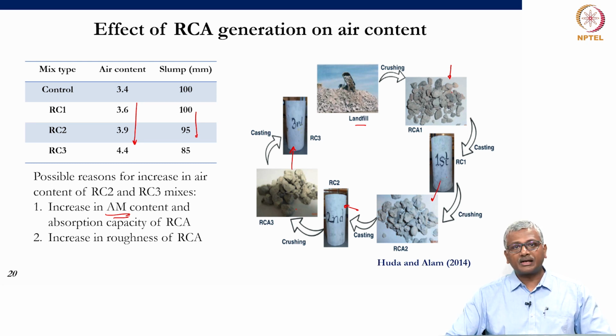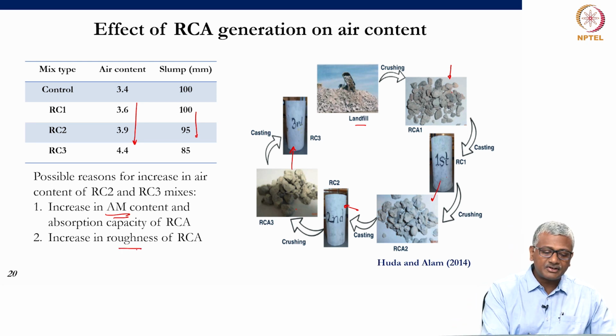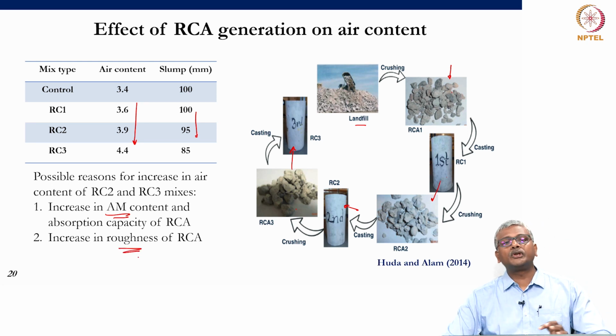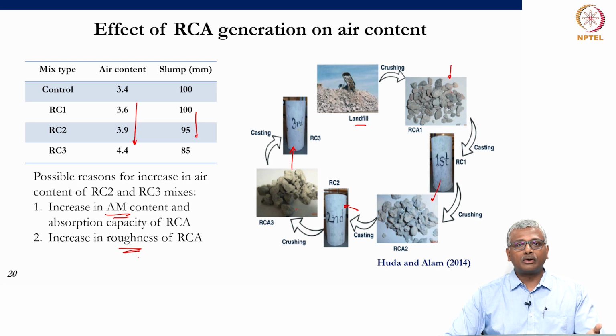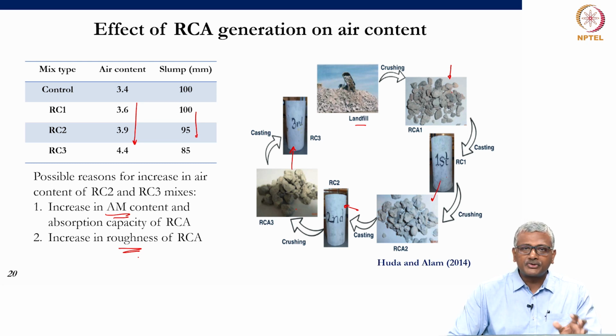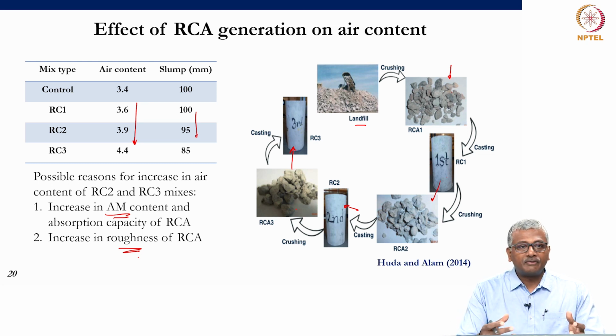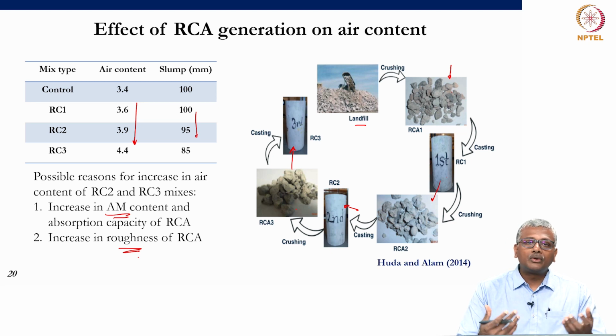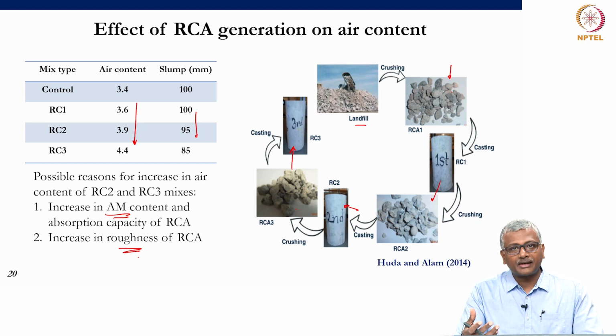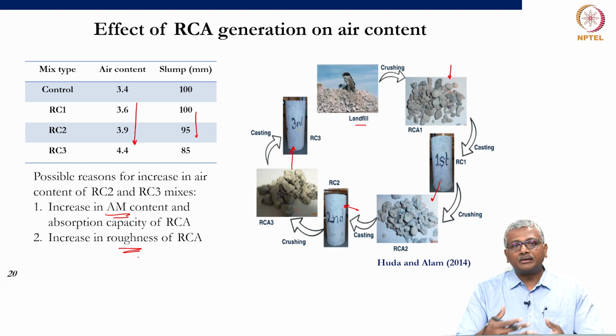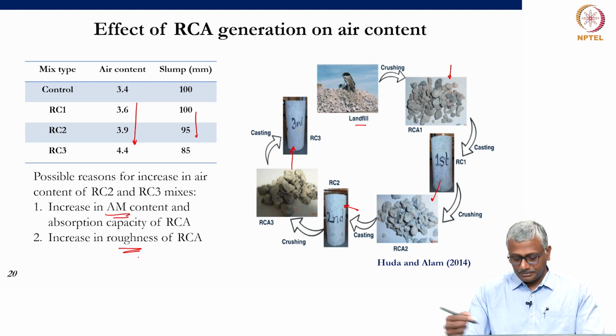And because of the continuous crushing and reforming, you are probably increasing the roughness of the RCA also, which is going to lead to this increase in air content and decrease in slump. But of course, this is only a study which is done out of interest. You don't probably know when you collect aggregates from a dump yard, right? You don't know how many times they've been recycled. You have no idea, right? But you need to obviously study if the aggregate characteristics are good enough to be used in concrete and then design your concrete accordingly.